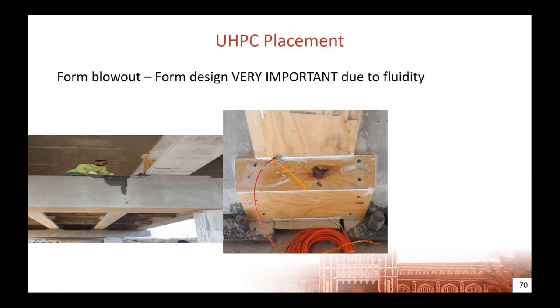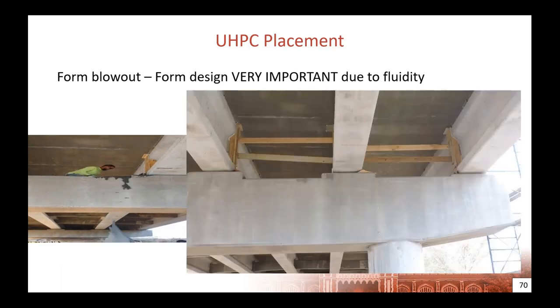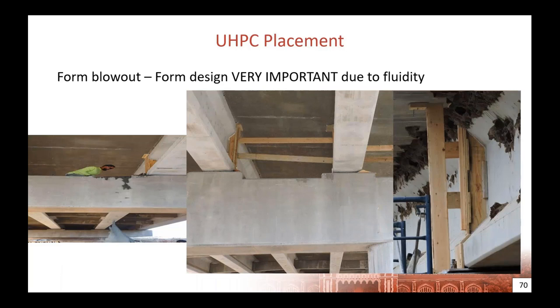And we had told the contractors that this material does maintain fluidity for a very long time. It tends to have an initial set time around 7 to 9 hours, depending on the material. And so it maintains this fluidity and this head pressure in the forms for a long time. So for future pours, the contractor didn't want that to happen again. So they braced the interior formwork against opposing joints and added extra TAPCONs where needed.